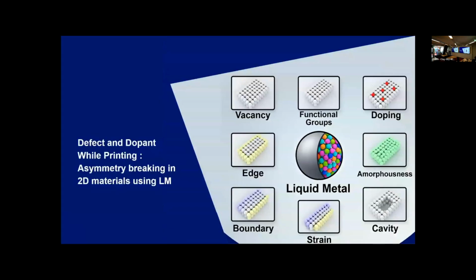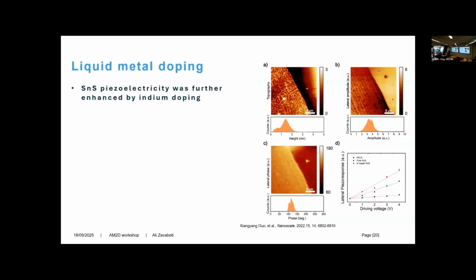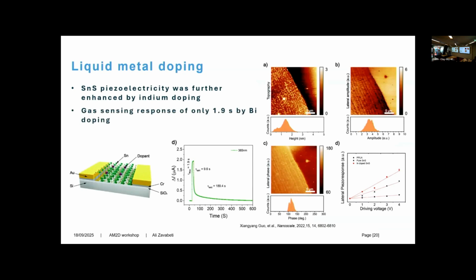Next are unique opportunities in liquid metal printing in engineering the skin. We can also engineer the vacancy and doping and so on. What one of my students did was with SnS, which I introduced earlier, one of our materials of choice for piezoelectric material. He substitutionally doped indium inside SnS, so we could improve the piezo coefficient by about 22.6%, and we also made gas sensors that could detect NOx, NO2 in less than 2 seconds, which is really impressive.